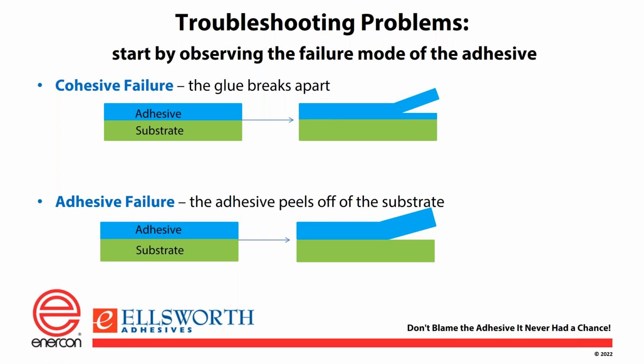A very simple rule of thumb as far as troubleshooting is to look at the mode of failure of the adhesive. So there are two main modes of failure that are typically observed. The first is cohesive failure. In this case, the glue or the adhesive breaks apart internally. You would observe the glue still stuck to the substrate, but the glue itself has broken apart internally. The second is adhesive failure. In this case, the adhesive remains intact. It keeps its integrity, but it actually peels off of the substrate.